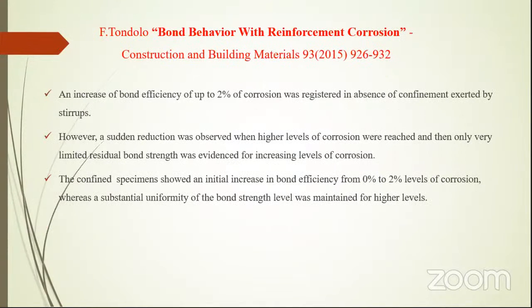The next literature study is about bond behavior with reinforcement corrosion. This paper says that an increase of bond efficiency of up to 2% of corrosion was registered in the absence of confinement exerted by stirrups. However, a sudden reduction was observed when higher levels of corrosion were reached, and then only a limited residual bond strength was evident for increasing levels of corrosion.